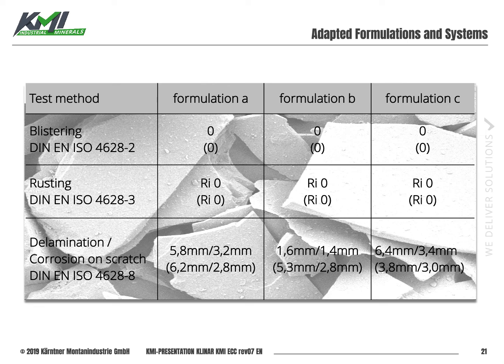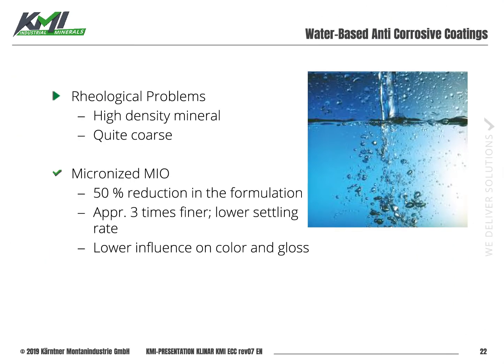That means as an outcome of this test series, you can reduce the necessary amount of MIO almost down to 50% and you get the same performance compared to the standard grade, and you can cut back the dry film thickness of the coating while keeping the same performance. These test results led to a number of new application possibilities with the micronized grades, and all these applications are already commercialized. That means we have customers doing that.